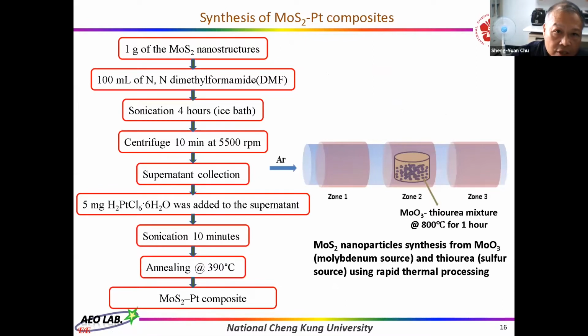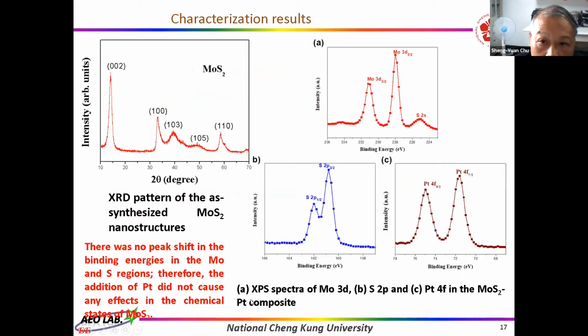This flowchart shows the synthesis of the MoS2-Pt composite, which is similar to the MoS2 material. The only difference is we use the H2PtCl6 compound as the Pt source. And also the nanoparticles were annealed at 390 degrees, and then we can get the MoS2-Pt composite. Also, the X-ray pattern of the synthesized composite is similar to the MoS2.